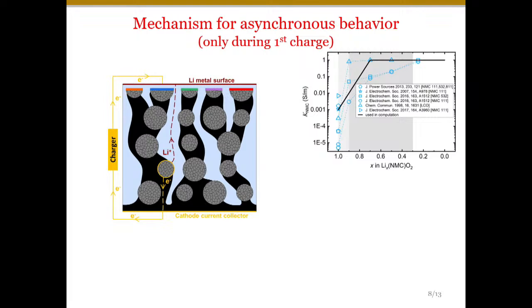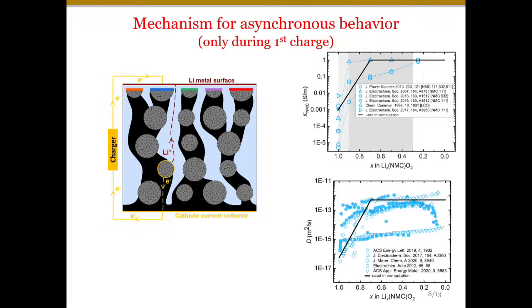Now the second question becomes why this asynchronous behavior persists only in the first charging process. We looked at the diffusivity values of NMC, and similar to electrical conductivity, we find that it varies by 1 or 2 orders during the initial time when lithium is taken out. This creates a situation where it is easier to take lithium out of NMC, but very difficult to push it 100% back.